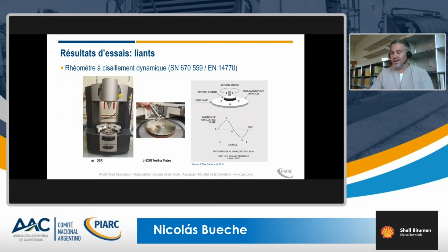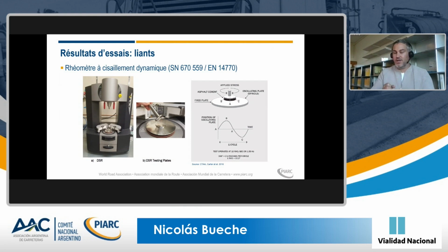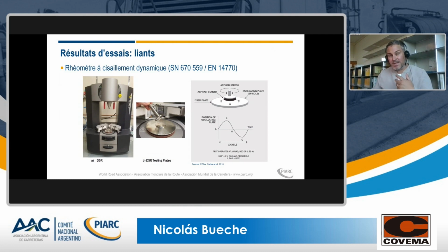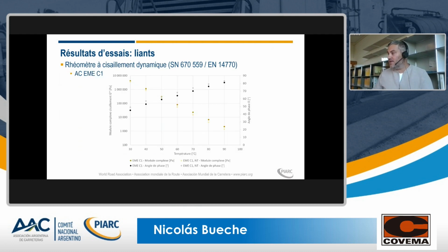A very short summary: using the DSR, we analyze the rheological behavior of asphalt. You pour a very small quantity of asphalt, and you apply a shear loading with a given frequency, sinusoidal loading, and then we can see the behavior of the binder. We made some extensive tests using the dynamic shear rheometer, and this is what you can see here for the C1 mixture. Do not forget it's a logarithmic scale, so a very small difference on the graph can be quite a big difference in the binder scale. We could see, for instance, that the hot mix has a bit higher stiffness than the warm mix, which is quite logical, once again considering the aging, and also that the warm mix has a bit higher phase angle than the hot mix alternatives.